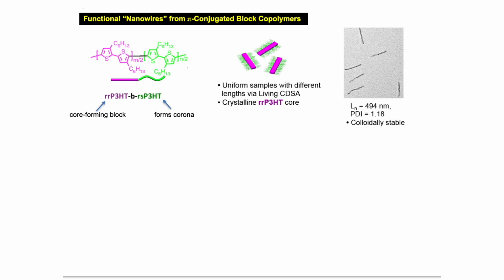So nanomedicine is an area we're working in. Another area you can work in, if you choose a core forming block that will conduct electricity, is to make, for example, nanowires. So we use this polymer made from a core forming block, which is a crystallizable polythiophene, and then we have a corona forming block, which is a polythiophene that will not crystallize. And you can assemble these into fiber-like micelles by living CDSA.